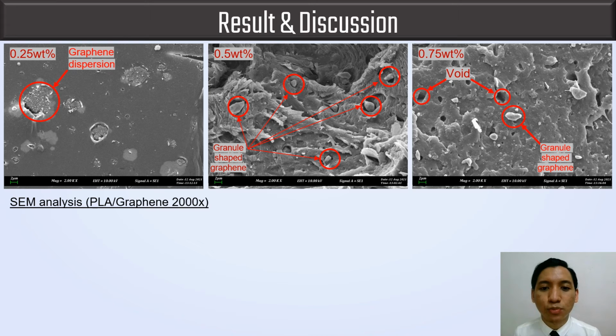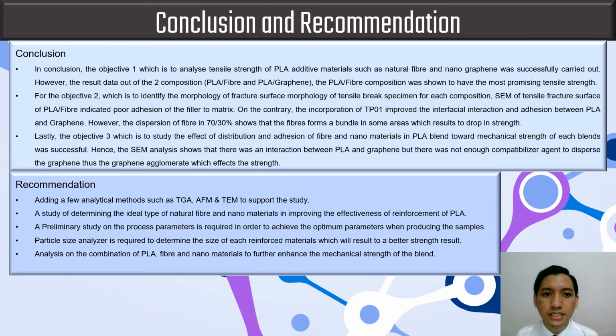However, in the case of the 0.5 and 0.75% graphene blends, the distribution of graphene forms irregular-shaped granules throughout the matrix. On top of that, the PLA blend surface becomes rough due to the filling effect of this granule-shaped graphene in the blends. The voids and granule-shaped graphene indicate that there is no interaction between PLA and graphene for the 0.5 and 0.75% blends.